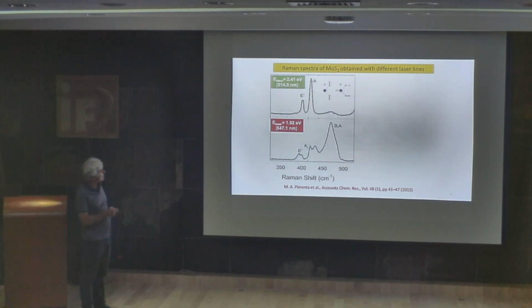Then this is the same sample of one layer of molybdenum disulfide excited with the green laser, the green laser that you have here. Then you can see those two peaks. That's a normal Raman spectrum. The E peak is the in-plane vibration of the atoms in the plane, and the A peak is the vibration of the atoms out of plane. These are not at resonance with the exciton.